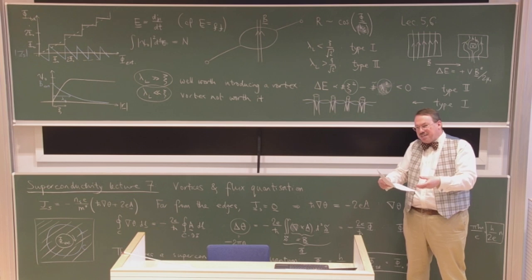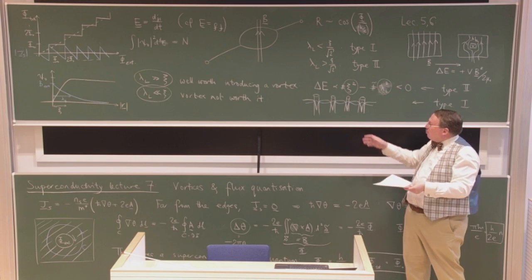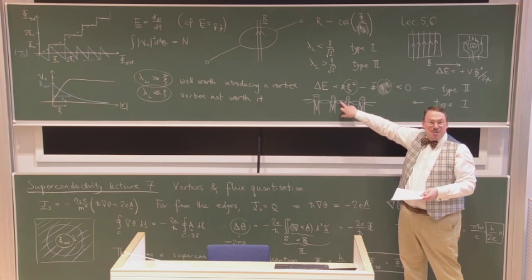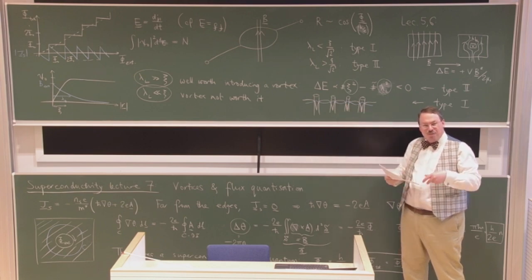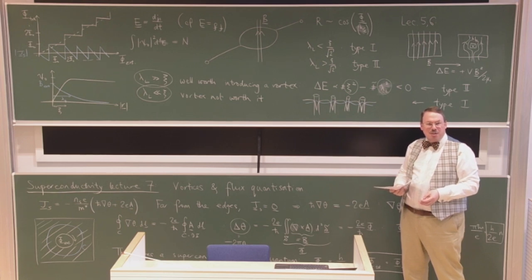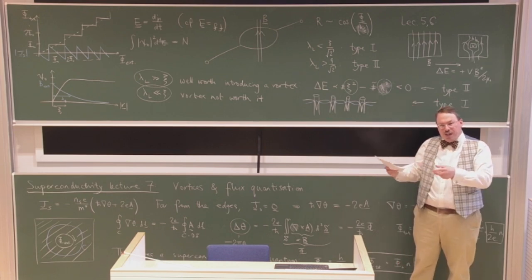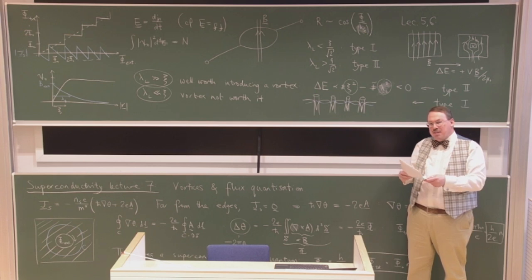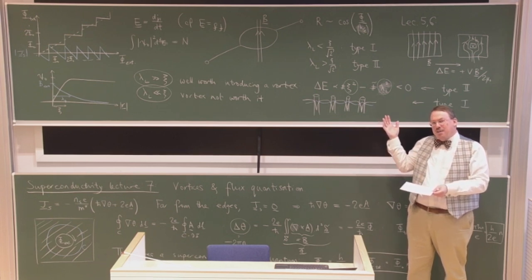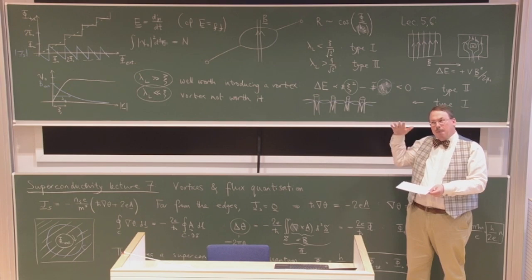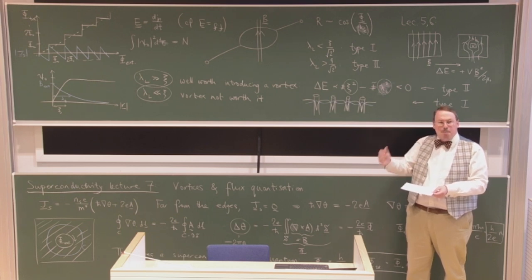And then at some vortex density, they depin, then they start flowing. You've still got superconductivity in the sense that you have the order parameter non-zero, but now you don't have a resistive signature of superconductivity because you've got resistance coming from the flow of the vortices through the sample. So it actually gets quite complicated once you ask what real superconductors do, but a lot of the understanding of what real superconductors do is based on this idealized picture that for a type 2 superconductor, at relatively modest fields, even while it remains superconducting, it will start admitting these vortices.